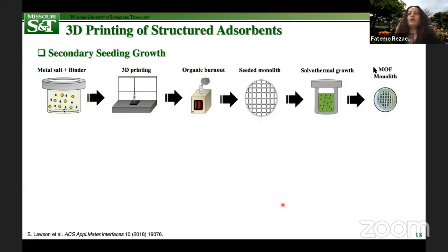All right, now moving on to the secondary seeding approach. The method, again, is schematically shown here for MOFs. So from this procedure, a mixture of binder and metal salt is first mixed in a solvent, and then by adjusting the paste viscosity, it could be printed into a desired structure, followed by organic plasticizer removal to yield the seeded monolith. In the next step, this seeded monolith was used to facilitate the MOF growth by a solvothermal synthesis approach, which gave rise to self-standing MOF monoliths.